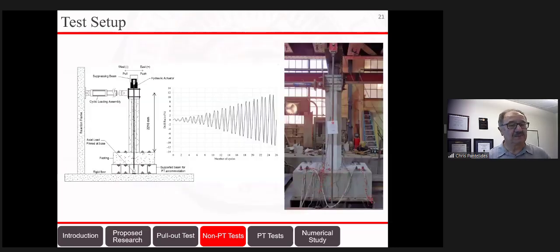So in order to study the seismic performance, we actually built on the strong floor, we attached the footing, and then we lowered the column inside the ducts. We grouted the ducts, and after 28 days, we were able to apply the lateral load using a servo control hydraulic actuator. It has a capacity of 800 kilonewton and an overall stroke of 610 millimeters. We also applied an axial load through these threaded rods. The axial load was typical for columns of this nature, about 6% of the axial capacity of the column.